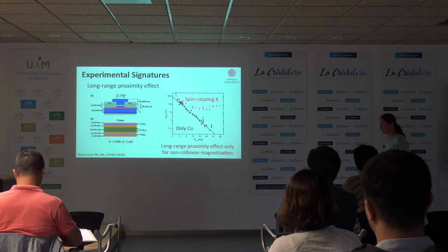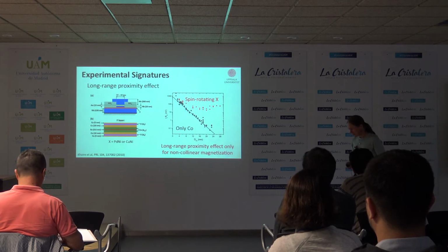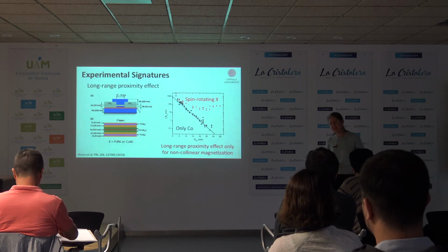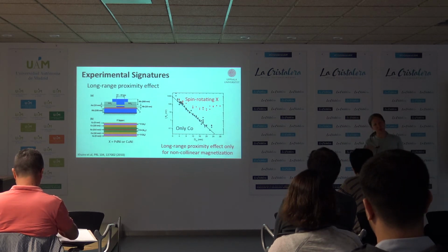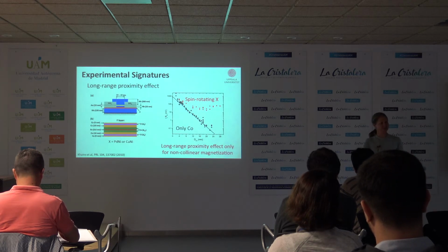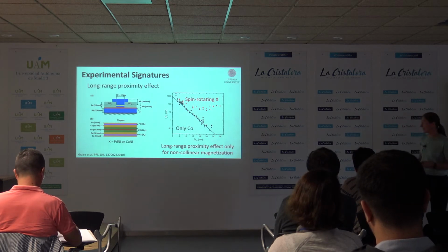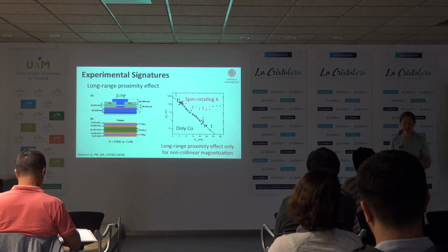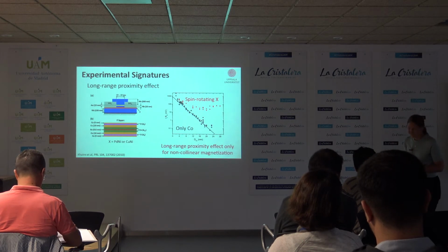Part of the problem is that the odd frequency state is definitely a dynamic state, and it's also kind of hidden, because if you have something where you integrate over frequencies, it falls out. If you measure at zero frequency, it's also zero. So you have to have something much more intricate in how it treats the frequency domain. We have a couple of ideas we're working on, but there's nothing yet. I think it's currently a big problem in the field. Some Josephson thingy with a time.